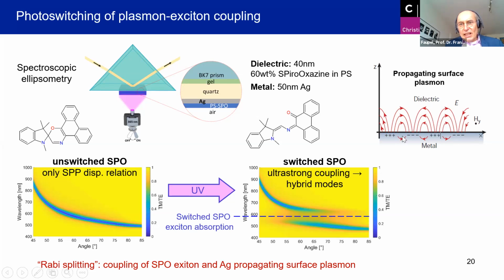And those propagating surface plasmons you cannot excite directly by shining light on. You need a plasmonic coupler. This is due to K-matching, and so typically one uses a prism to excite such surface plasmons on the surface of metallic films. And the example I've chosen here is a silver film. And what we want to do here is we want to reversibly switch plasmon-exciton coupling. So the final aim is all optical switching here.